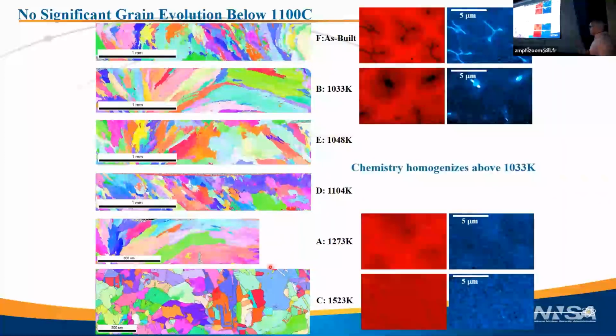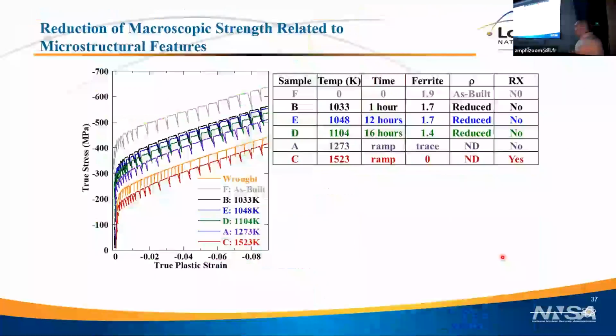And finally, the chemistry, you see the chromium dissolves up here, again, above 1100 C. Okay, so here we have chrome segregated in the as-built material. Here it's starting to dissolve a little bit. By this one at 1,500 C, the chrome is completely dissolved. So you see now we've looked at where all 4 of those parts of the microstructure go away, and I can summarize that in a table. So these are the different samples, the heat treat conditions in terms of time and temperature, the dislocation density, how it's changing, what the ferrite's doing, and then recrystallization.